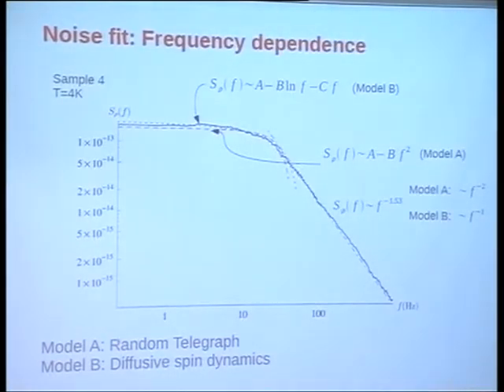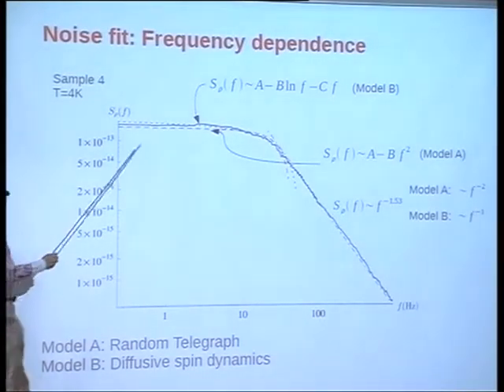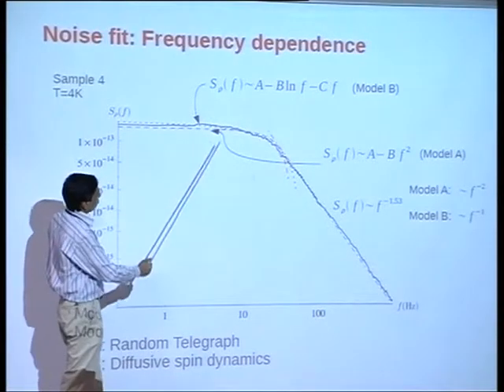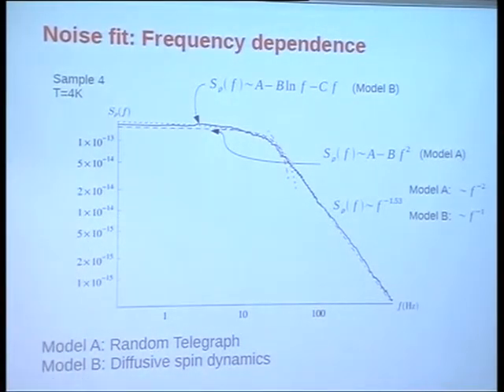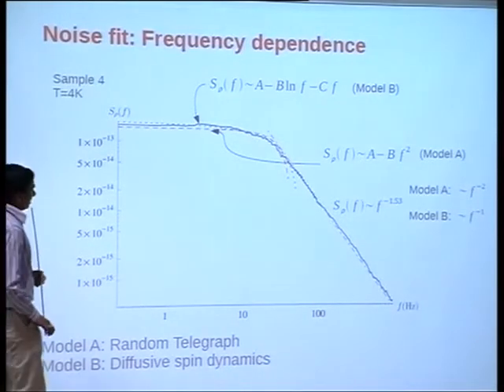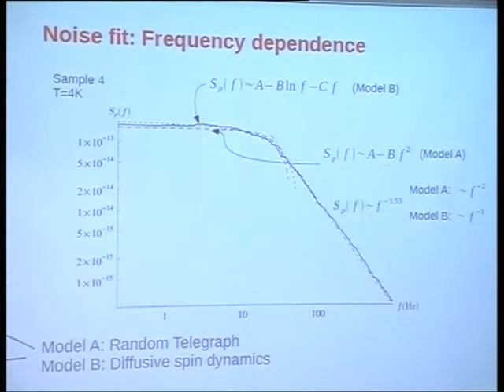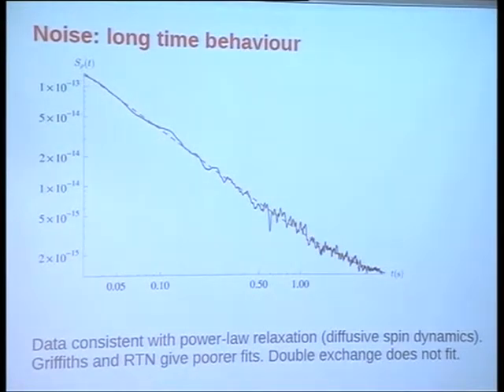Okay, so first I try to fit the frequency data. In the case of model A, I will get a telegraph noise. In the case of model B, I'll get something different. But with this range available here, where so much data is being shown, I can fit it with both, which does make me very happy. So both model A and model B seem to be doing fine here. But things get better if I go to low frequencies or long times. So I can take the Fourier transform of the data and look at the long time behavior.